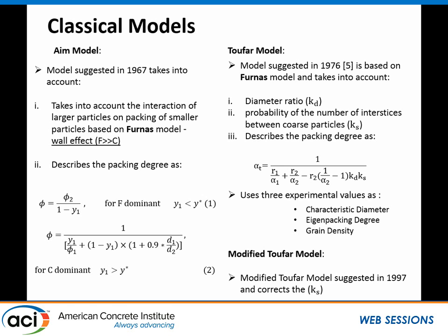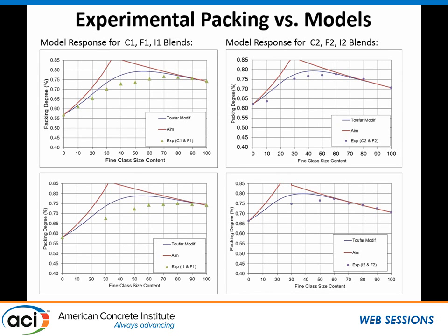But the Toufar model used three experimental values to build the model, starting with the diameter ratio of the particles. We're talking about binary mixtures here. From coarser to finer, that is the diameter ratio, and then the probability of the number of interstices between the coarse particles comes in as a factor in the equation, and it is also looking for packing. The modified Toufar model, as mentioned in the previous presentations, makes a slight change based on the assumption that not every fine particle is surrounded by exactly four coarse particles, which is initially assumed in the Toufar model.